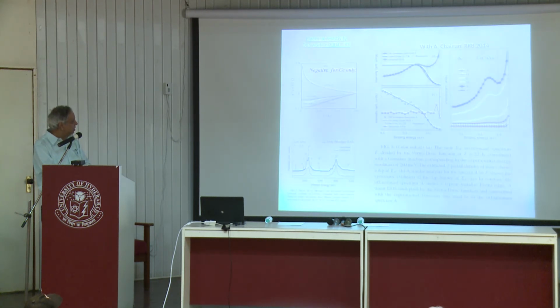The other important thing is very transparent. Anybody can look at the figure. This is electric resistivity as a function of temperature. If you keep increasing the hybridization, at some point you will find that even the transport behavior is very funny with reference to other compounds in the same family. For example, if you look at lanthanum, we have one series, lanthanum copper arsenic 2, lutetium copper arsenic 2, yttrium copper arsenic. They look like sort of metals here. The resistivity as a function of temperature is normal, a positive temperature coefficient.